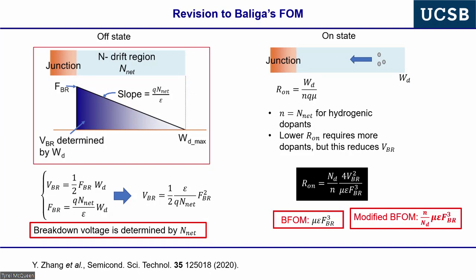So the on-state resistance actually depends on the available measured carrier concentration, N, times q times mu. This is the conductivity. The resistance is 1 over the conductivity times the thickness of the semiconductor. This is actually what gives you the on-resistance, okay? For hydrogenic dopants, which follow hydrogenic doping models, the electron concentration at room temperature is typically very close to the net doping, okay? But if we have deep dopants, this is not the case. And so what Yuewei Zhang and I came up with is a modified figure of merit, which just accounts for the dopant ionization.